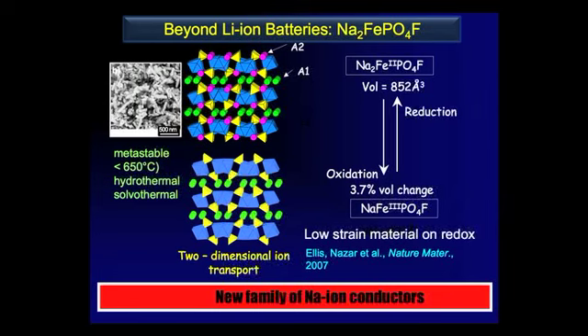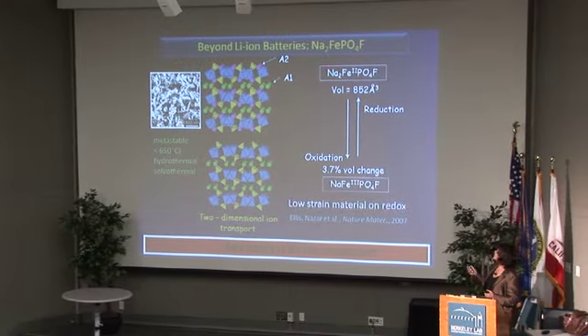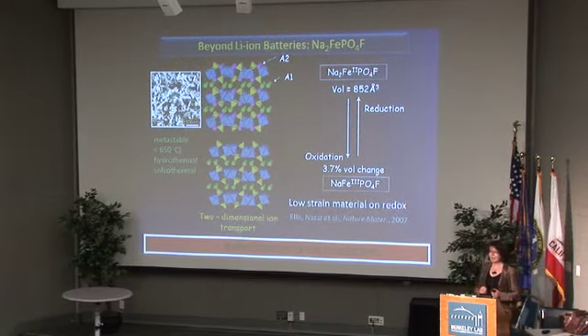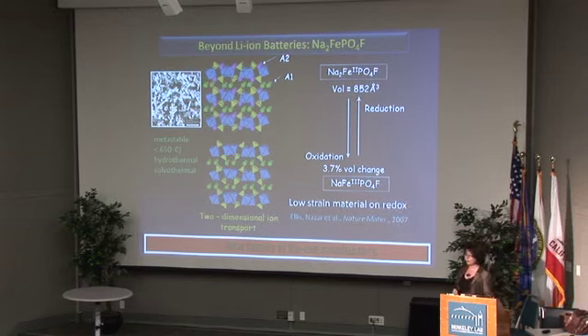And so that allows you to get away with a really low volume change of only 3.7% between the reduced and the oxidized form. And if you contrast this with lithium iron phosphate, the olivine, that's about 6.7%. So it has half of that volume change, which allows it to cycle much better. We call this a low strain material, and we reported this in 2007.